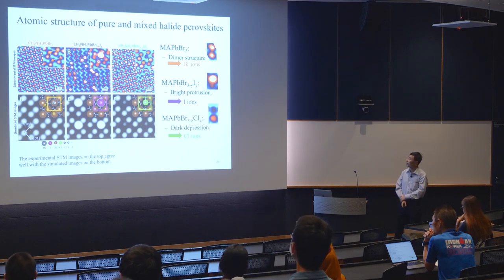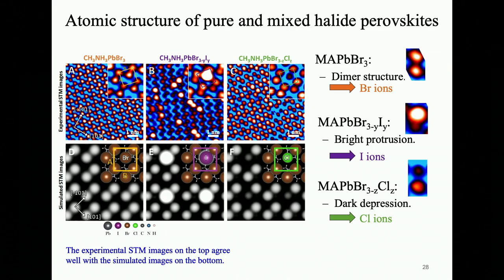On the other hand, by vacuum deposition of a small amount of PbCl2, we substituted part of the bromine surface ions with chlorine ions, because chlorine ions have a smaller ion radius than the bromine ions. They appear as dark depressions in the STM image.